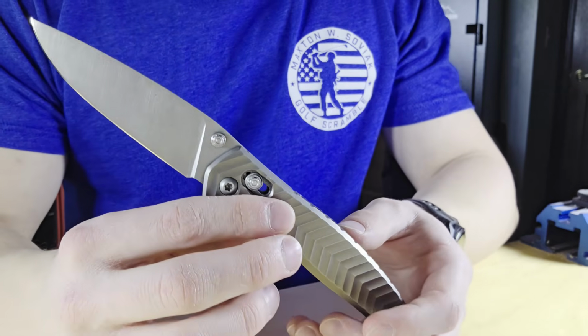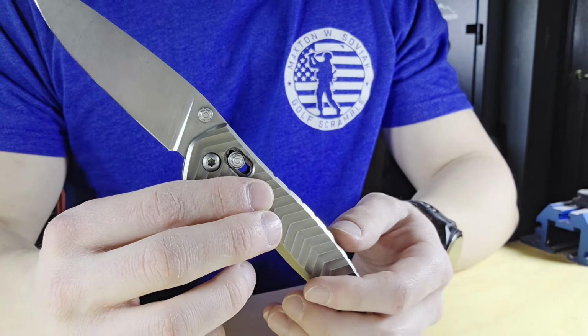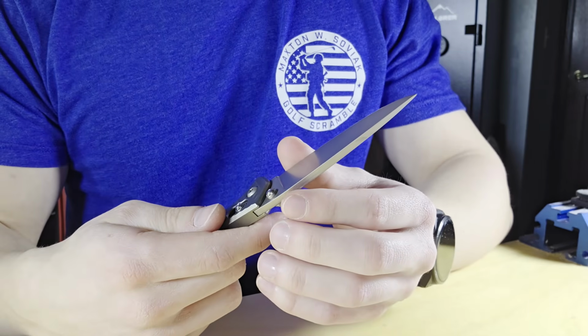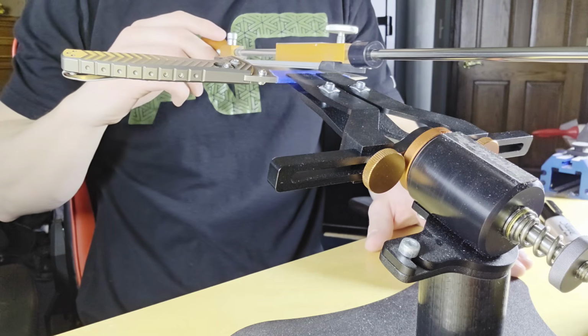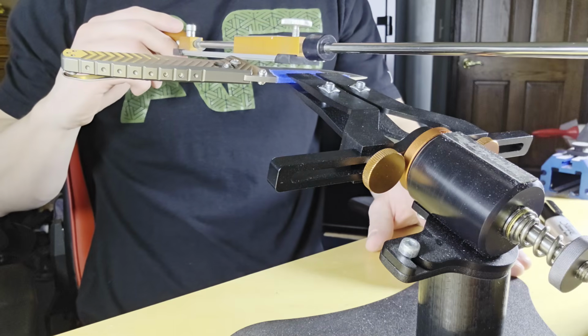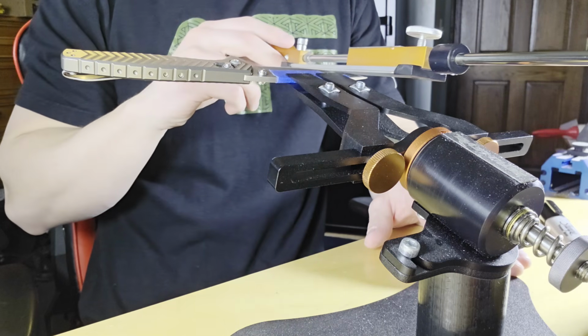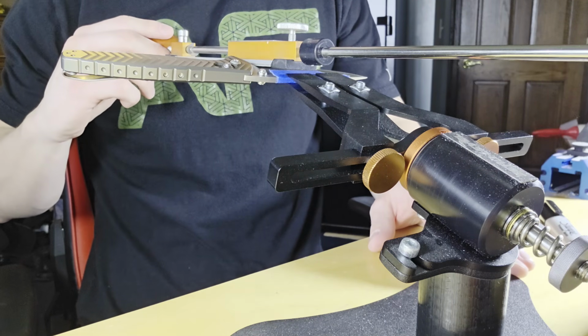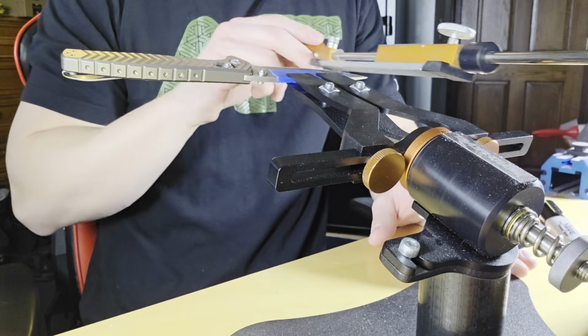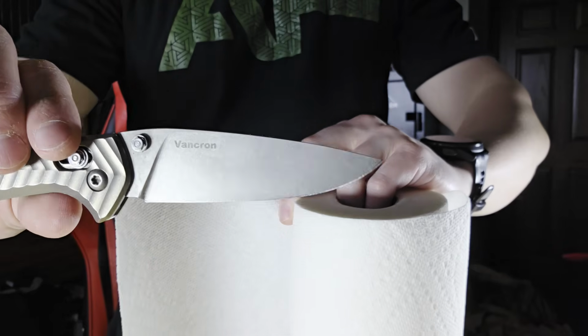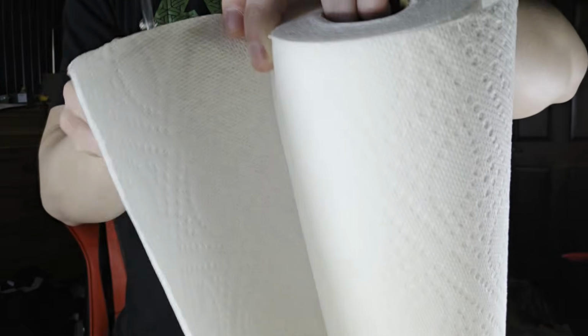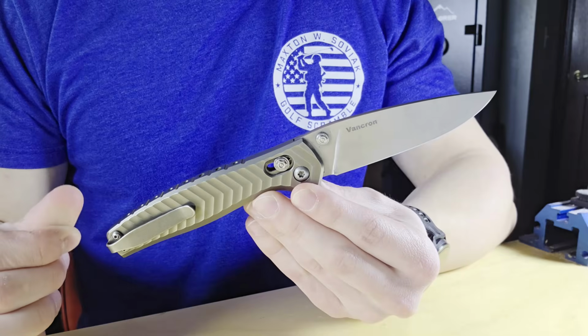So let's talk about sharpening on this guy. First sharpening was my standard progression of 200, 600, and 1000 grit diamond plates, followed by 16 and 4 micron CBN emulsion on leather. This came up very aggressive and sticky, and it cut free-hanging paper towel very, very easily. And it tested at 145 BESS on the BESS tester.